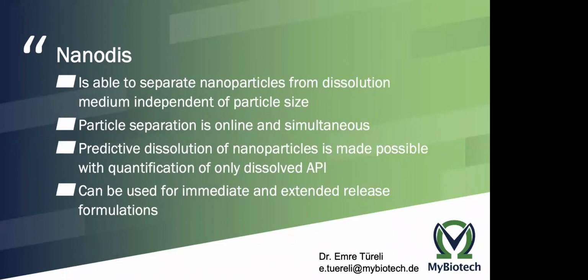So this is my last slide, just to summarize what we have reached with nanodis. With nanodis, we have a method which is able to separate nanoparticles from the dissolution medium, independent of particle size, since you can choose different cross-flow filters. Cross-flow filters starting with 1 kilodalton up to 1,000 kilodaltons give you the flexibility to choose the right cross-flow filter according to your needs. The particle separation is online and simultaneous. In the case of nanodis, it is a very quick separation method so that you can even use it with nanoparticles with a high dissolution rate.